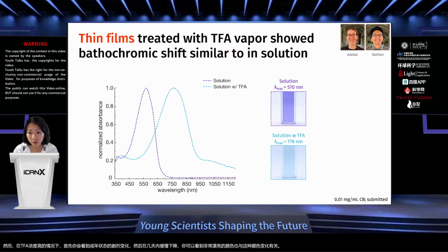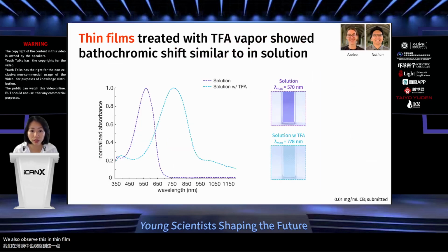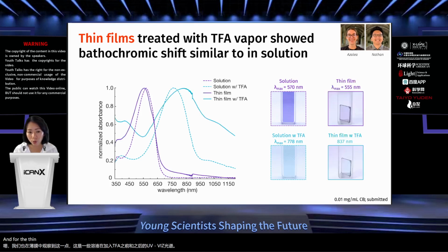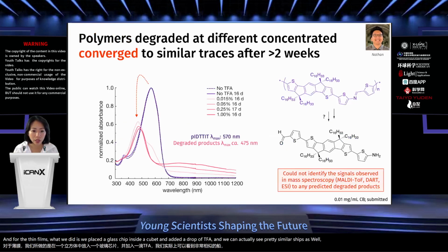We also observed this in thin films. So here is some solution UV vis spectra before and after TFA addition. And for the thin films, what we did is we placed a glass chip inside a cuvette and added a drop of TFA, and we can actually see pretty similar shifts as well.